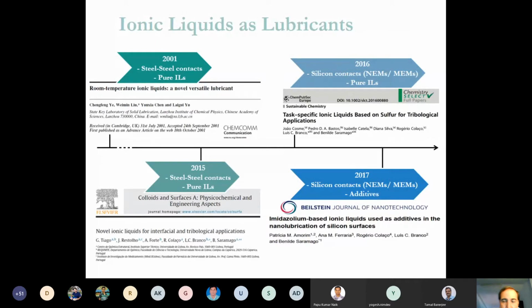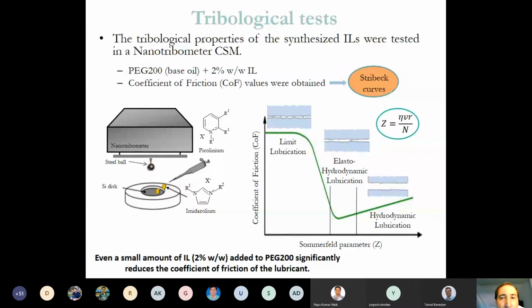and this is useful for nano-lubrication of silicon surfaces. What we are doing is testing the tribological properties in collaboration with other groups. We synthesize different kinds of ionic liquids and then apply them in a nanotribometer. And we compare PEG, the polyethylene glycol, that is the base oil, in the presence of ionic liquid as an additive, only 2% in weight, and we check the coefficient of friction values by Stribeck curves. The variation of this coefficient of friction indicates the regime, like boundary lubrication, elasto-hydrodynamic lubrication or hydrodynamic lubrication. And this behavior is possible to observe using this kind of studies.